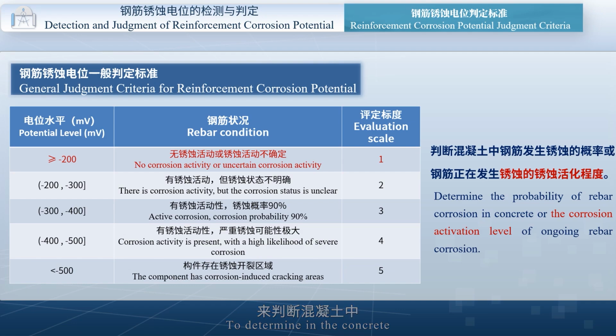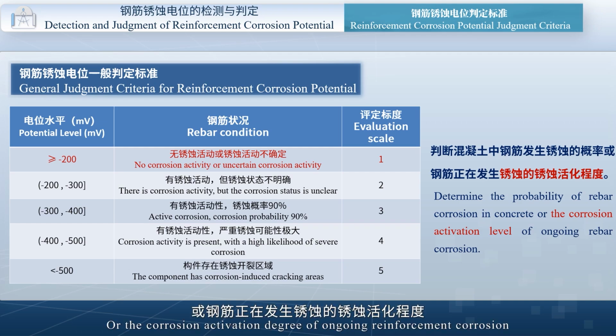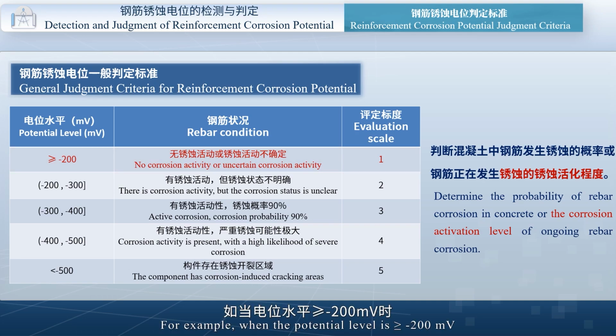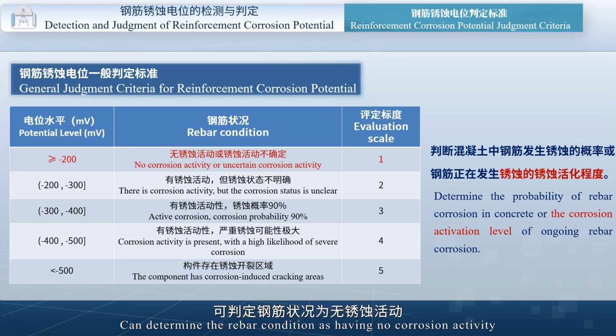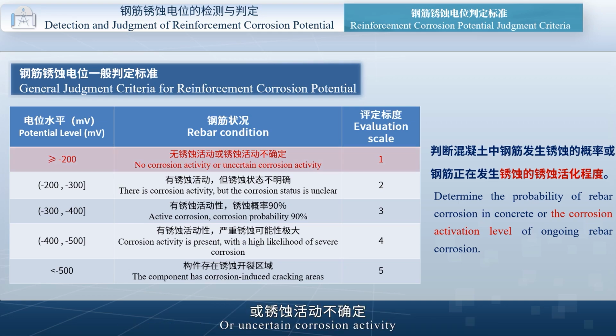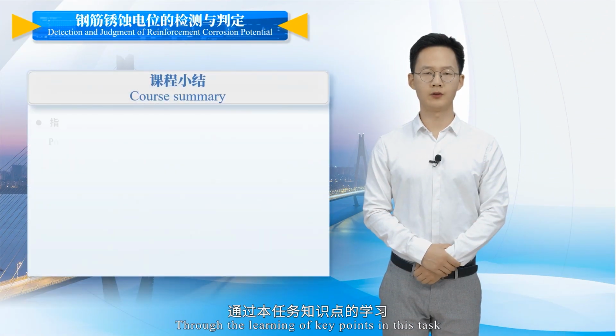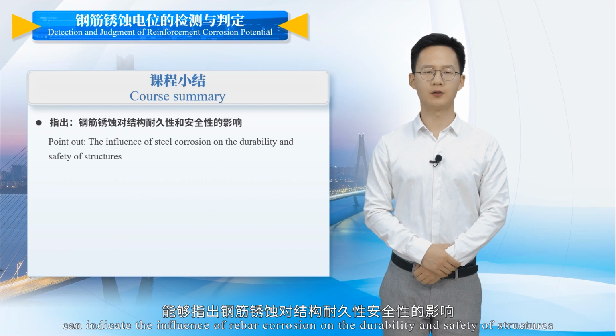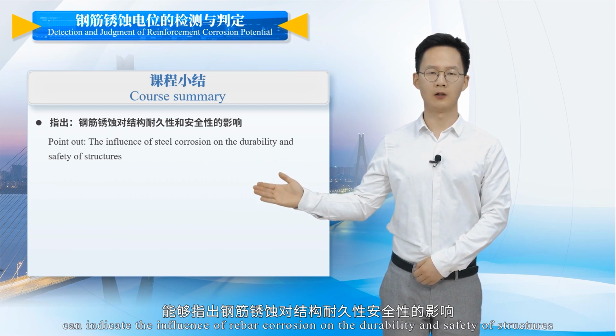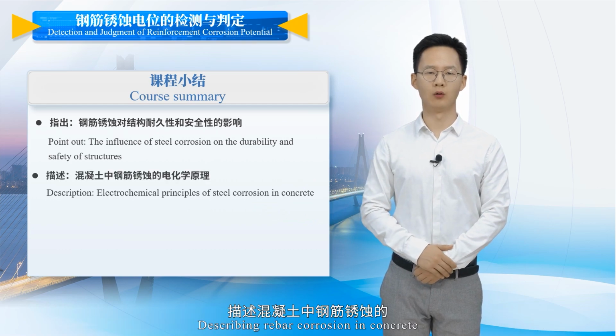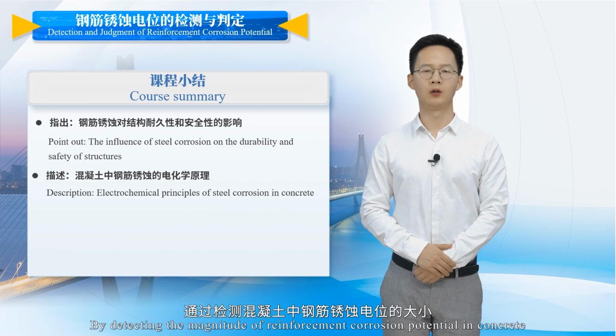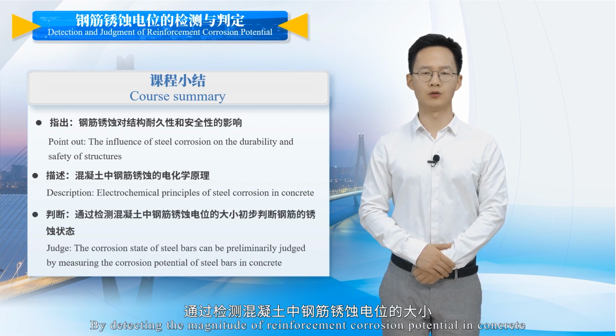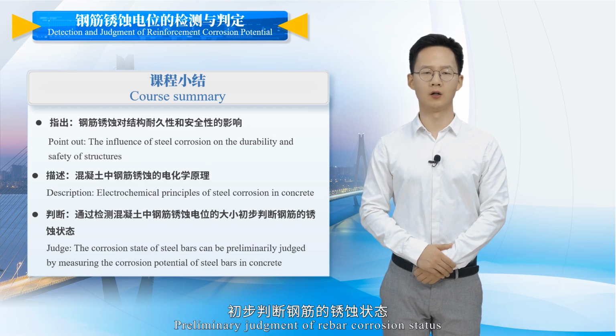This is to determine the probability of rebar corrosion occurrence in the concrete, or the corrosion activation degree of ongoing reinforcement corrosion. For example, when the potential level is greater than or equal to -200 mV, we can determine the rebar condition as having no corrosion activity or uncertain corrosion activity. Evaluation scale is 1. Through the learning of key points in this task, you can explain the influence of rebar corrosion on the durability and safety of structures, describe rebar corrosion in concrete, and explain the electrochemical principle. By detecting the magnitude of reinforcement corrosion potential in concrete, a preliminary judgment of rebar corrosion status can be made.